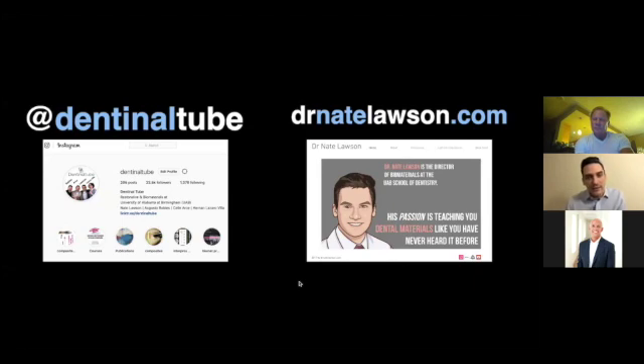If it's a non-retentive restoration, I don't like to use the self-adhesive resin cements, like for a non-retentive overlay or onlay. In that case, I like to apply some type of adhesive to the tooth. One of the controversial steps is whether or not to light cure that adhesive once it goes onto the tooth, because we've definitely shown in the lab that you can get higher bonds if you light cure the adhesive before you apply the resin cement.